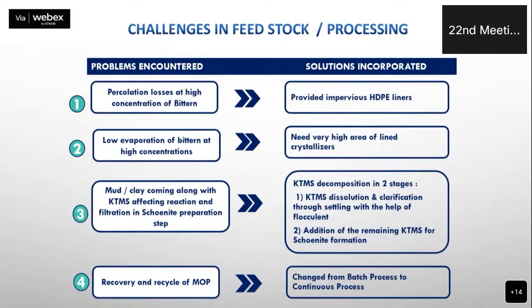And then along with the kainite type mixed salt, a lot of mud, clay, etc. was coming, which was affecting the process. So we dissolved the kainite type mixed salt and clarified it using flocculating agent, etc. And we did it in two steps. So first we dissolved and clarified it, and then in second step we added remaining quantity of KTMS to form the next product, that is schoenite.